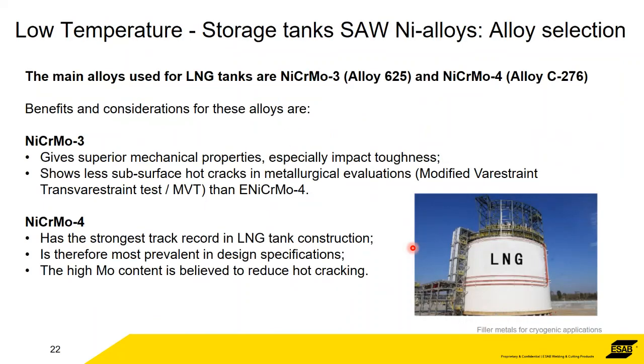So which alloys are used for these 9% nickels? The main ones by far are either nickel chrome moly 3 or nickel chrome moly 4, so alloy 625 or alloy C276. These are the two grades that have been used extensively over the years. We've certainly got lots of experience, and we've got literally hundreds of installations using either the nickel chrome moly 3 or the nickel chrome moly 4. The prevalence of 625, nickel chrome moly 3, is that it's really a commodity. There are a lot of people manufacturing this grade at the moment, so it tends to be cheaper. It's more readily available than the C276.